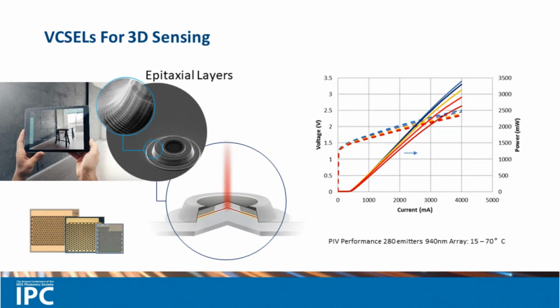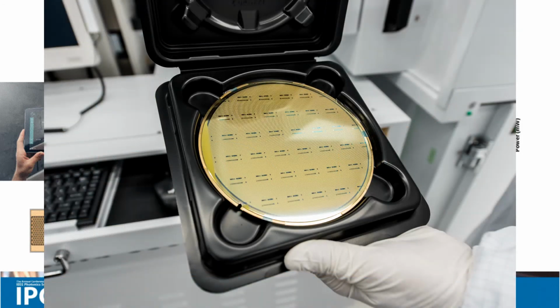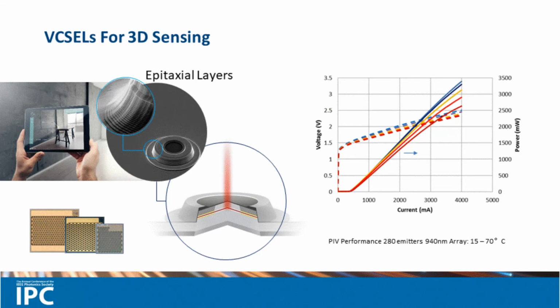Introducing dopants such as aluminum and indium to gallium arsenide for the different refractivity layers creates significant mechanical stresses that need to be managed across the array as well as over operating temperature. And these challenges become exponentially more difficult in moving to 150 millimeter diameter wafers, which were necessary to achieve the required commercial scale and costs. So you can see how VCSELs are yet another beautiful example of the marriage between material science and photonics.